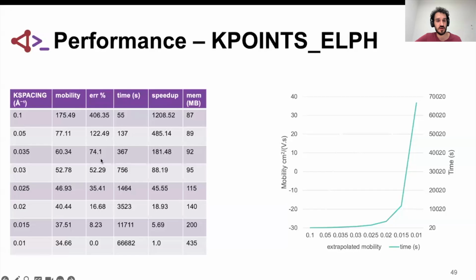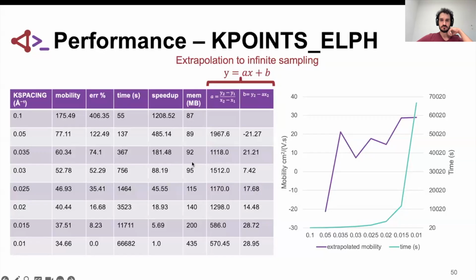Here the error is quite large, so using very coarse grids changes a lot the final value of the mobility that you get. So you really need to go for very dense meshes. It's critical to look at the convergence of this parameter, and the computational time increases very significantly. What I recommend in this case is to try to extrapolate the quantity you're interested in, the mobility, to infinity. Just use two points between different samplings and a simple formula to extrapolate to infinite sampling. You will see that eventually your value stabilizes and doesn't change anymore, so you know you are obtaining a reliable result.